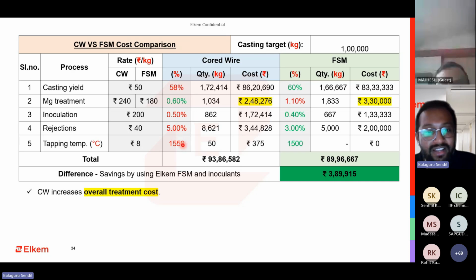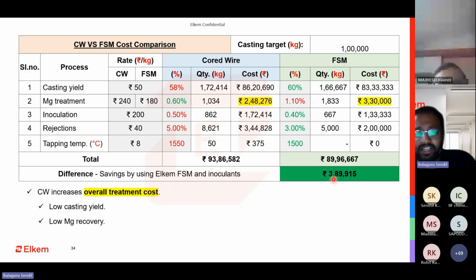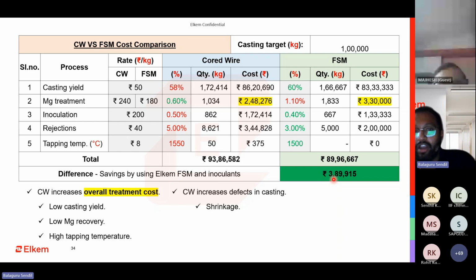With cored wire, you need to increase the tapping temperature because the time it takes to plunge is much more. So if you look at the overall cost of cored wire for a small setup also, taking into consideration the end-to-end picture, not only the treatment cost, it is always on the negative side. Because of the casting yield, the magnesium recovery is also lower. You need to increase the tapping temperature. The last one, in terms of defects, it creates shrinkage, dross, and carbides. These are the three things you have in it.